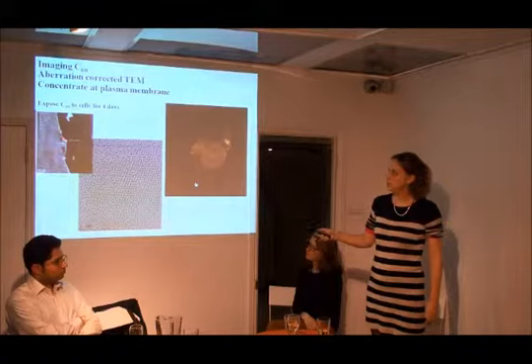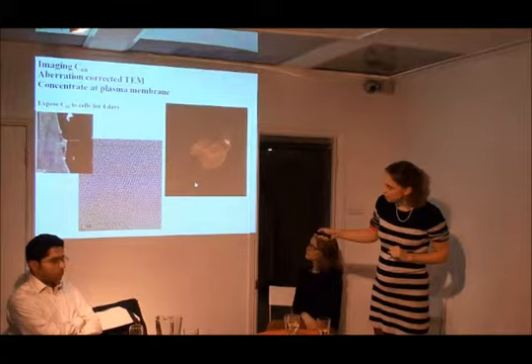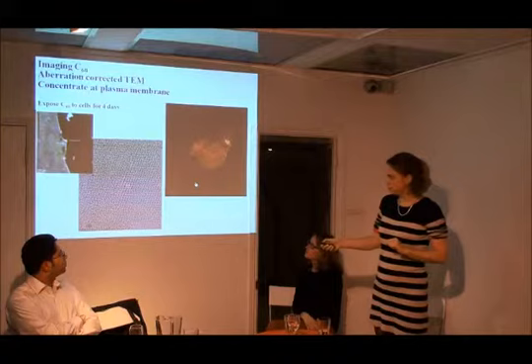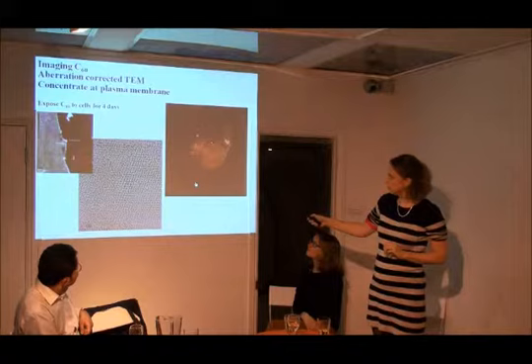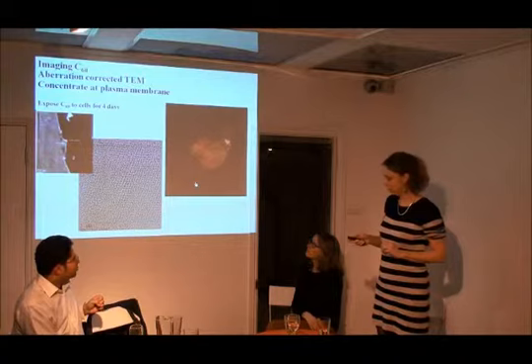So when you look at the outer membrane of the cell, bump up your magnification to see the individual C60 molecules, you can see here this lattice of individual C60 molecules, and they're segregating at the outer membrane of the cell. Another thing that happens is that these C60 molecules kind of crystallize to form an ordered structure. And so when you look at them in the cells, here's my cell with its nucleus. At the outer membrane of the cell, they aggregate as a crystalline structure inside the cells. So again, we can take 3D reconstructions to show that.